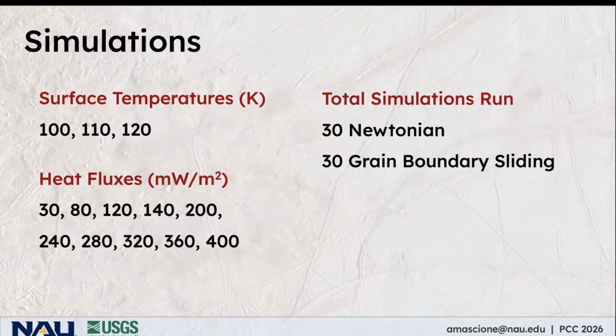So in total, so far we have modeled 60 relaxation scenarios. We implemented 3 surface temperatures and 10 heat fluxes for each surface temperature. This included more conservative, modern estimates of surface temperature and heat flux, as well as some significantly higher values that might represent past conditions.